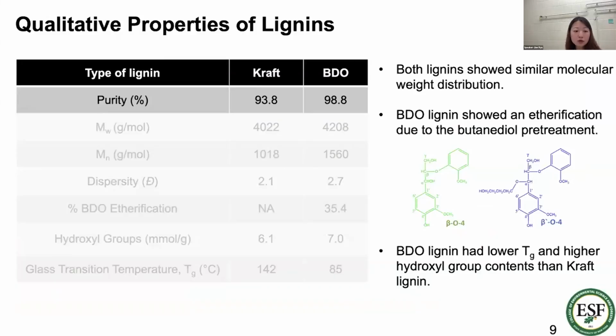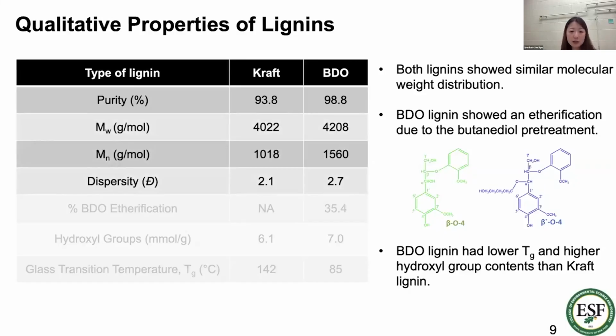Before we begin the modification, we want to see the characteristics of kraft lignin and the BDO lignin we produced. The purity shows that the kraft lignin showed around 94%, and BDO lignin showed around 99% purity. How about the molecular weight? Molecular weight was quite similar between kraft lignin and BDO lignin, 4,000 grams per mole for both.